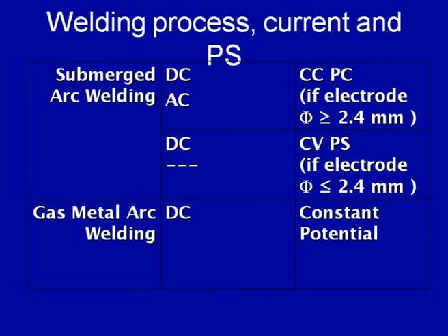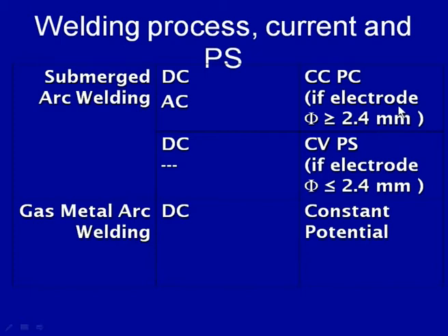While in case of the submerged arc welding process, DC and AC both can be used, but normally the constant current type of the power sources are used with the large diameter electrodes greater than 2.4 mm size in case of the steel electrode welding, because in case of the large diameter electrodes, the constant voltage power source does not help to get the self regulating arc.